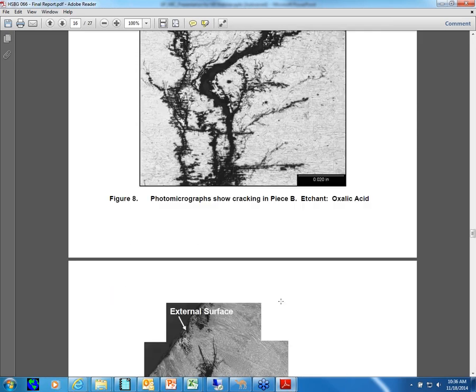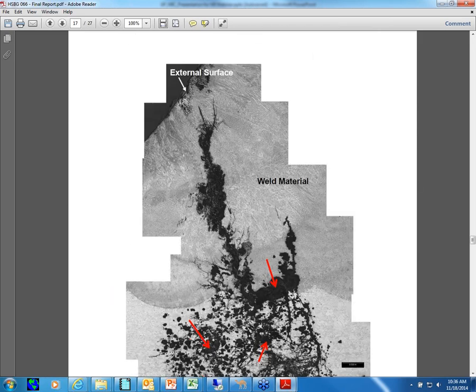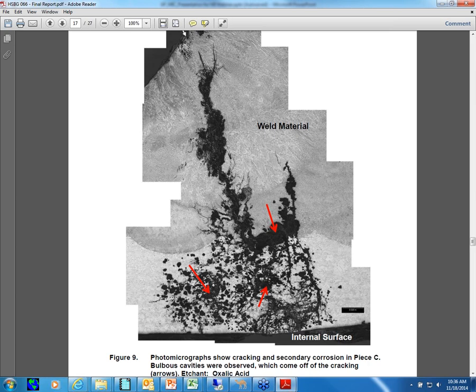But what you find, if you read more and more in depth into the literature, especially in this case where we've got manganese oxidizing bacteria, is that the bacteria actually create a very low pH environment and attract chlorides to it. They form heavy metal chlorides in that environment, even though the base water, the water outside the microbial colony, is extremely low in chlorides, like 13 parts per million, which is very, very low, especially for our industry. You can get extremely high concentrations of chlorides beneath the tubercle and actually cause the corrosion you see in the picture in front of you.